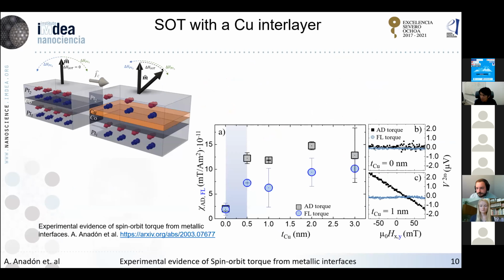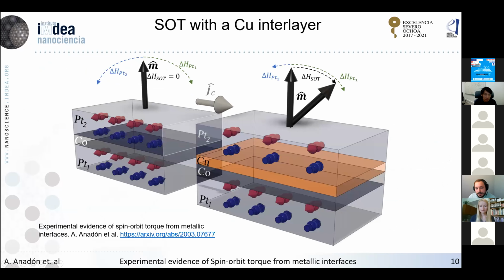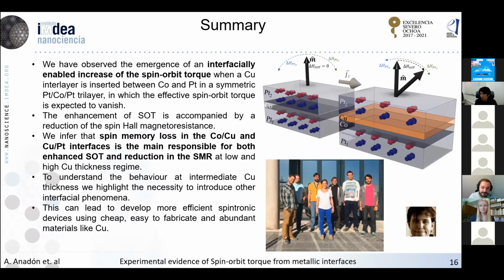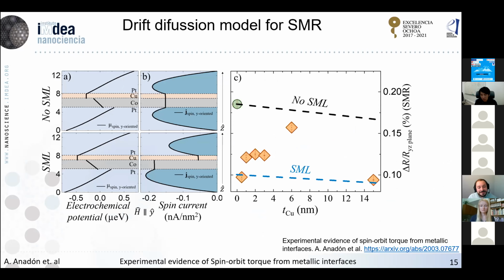Okay, so a question from Felix. Do you know why you have the thickness dependence of the spin memory loss? So what we think here is, as I said, this is a very challenging interpretation because you have many different things at the same time. You have the spin filter, and you have the spin precession, and you have the spin memory loss, and these three effects have a strong dependence on the copper thickness. They are not isolated to this dependence. So basically, you have three things going on at the same time, and separating all of them is challenging. So what I say is this is like the composition of several interfacial effects.